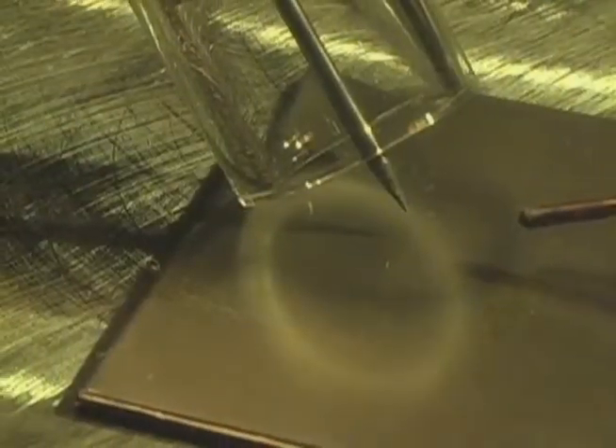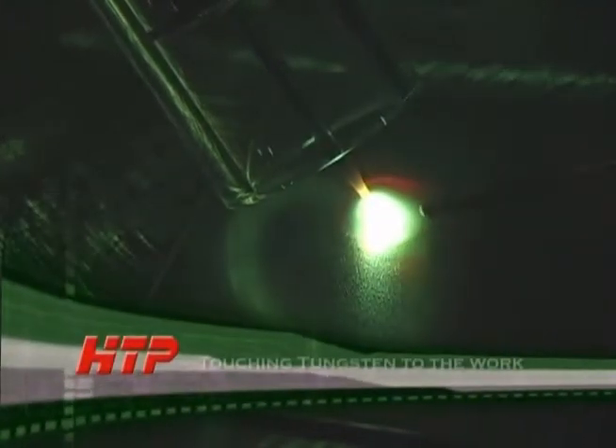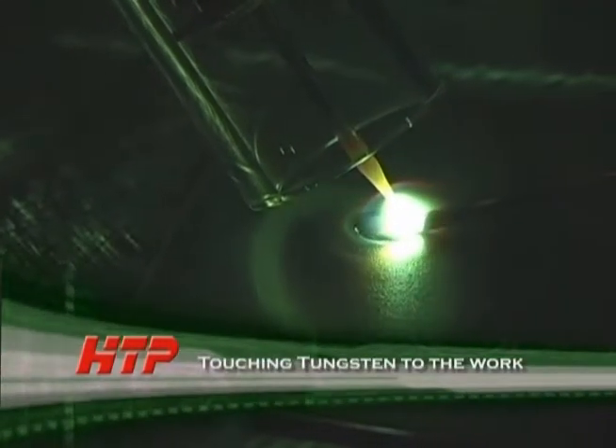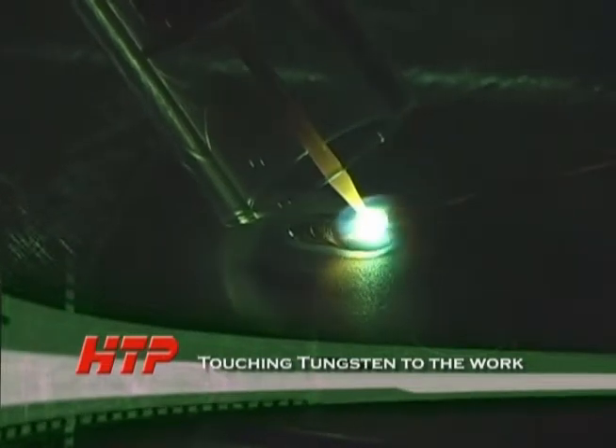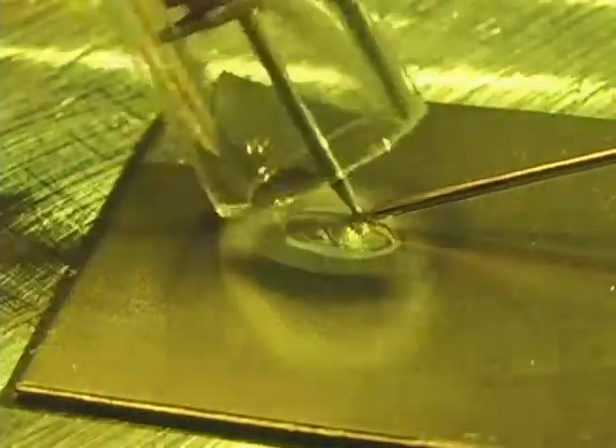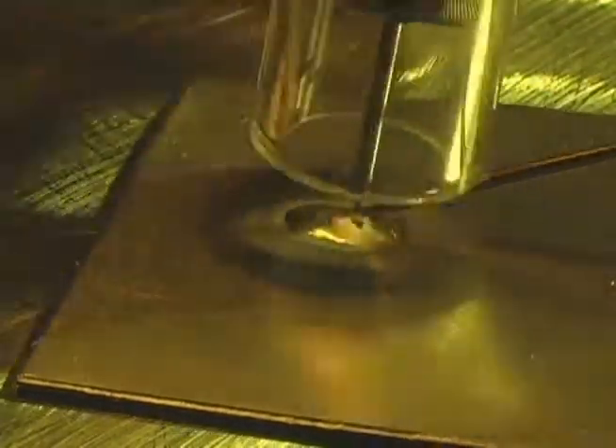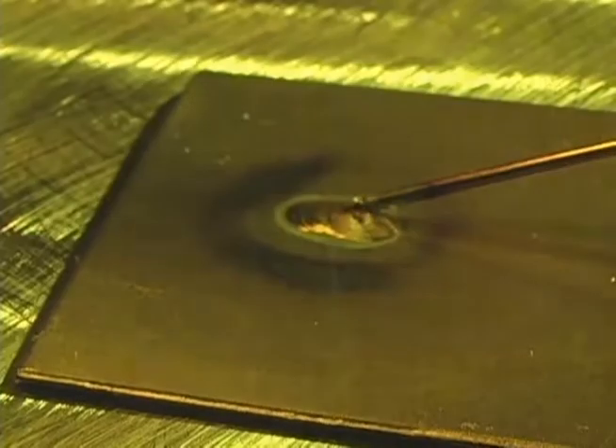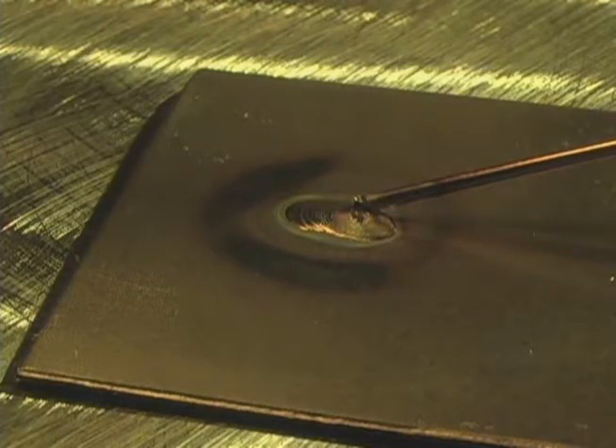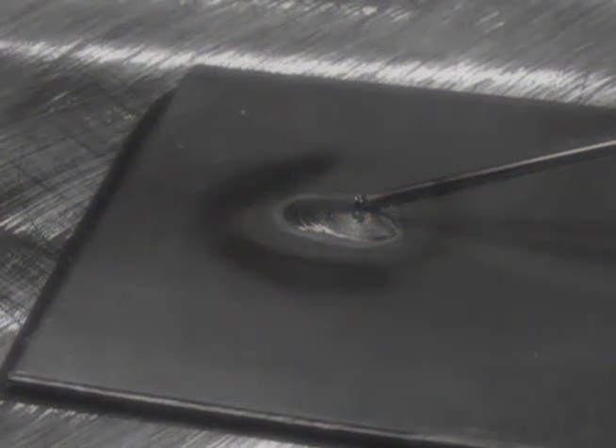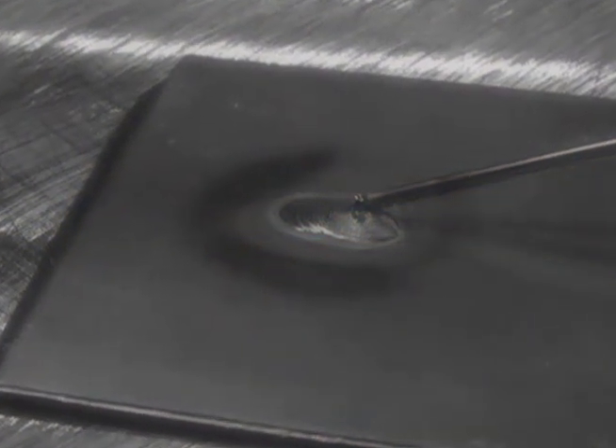Here is another common mistake. Let's face it, we have all done it. You are welding along, trying to keep your tungsten as close to the work as you can, and you touch the tungsten to the work. In this instance, the tungsten stayed in the puddle too long and extinguished the arc. The tungsten became stuck in the molten puddle when the arc extinguished and the puddle cooled. The tungsten must be removed from the torch and sharpened.